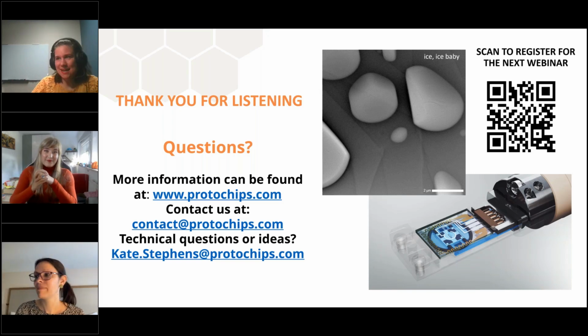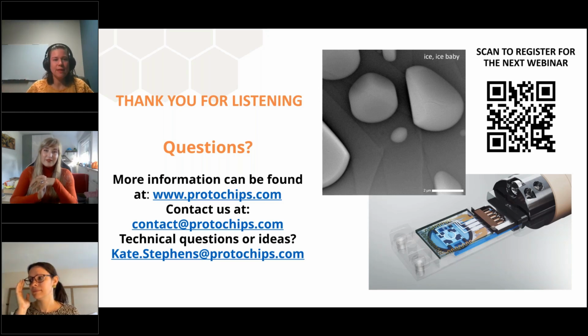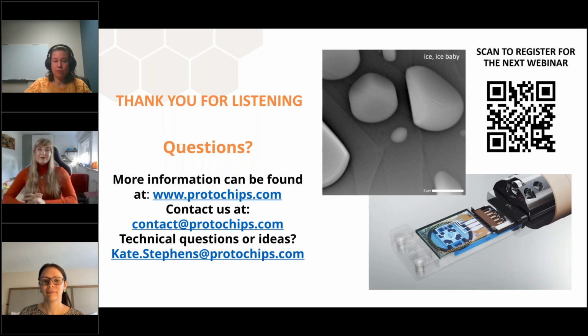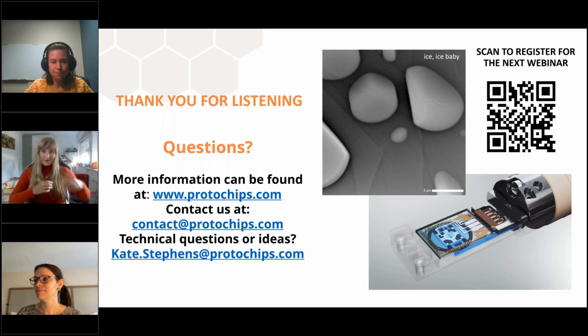Yeah, so that's actually one of the reasons that's on my slide, is I wonder the same thing. The way that I would design the experiment if I were the one doing it would be that I would have my reference electrode set up. I would figure out what my reference potential is, and then I would cool at the tip and see how much it shifts. And then I would cool the external reference electrode as well, and see if that brings it back or if there's any shift at all, because there very well might not be.